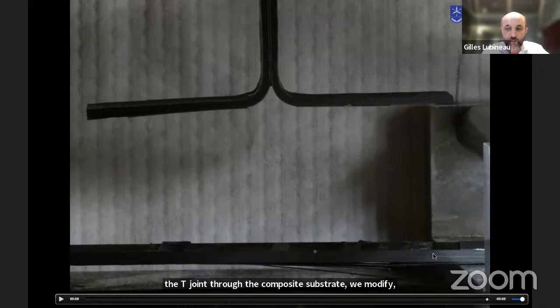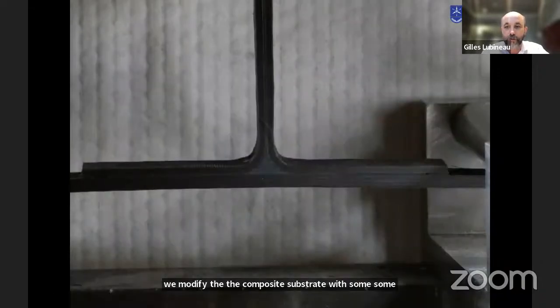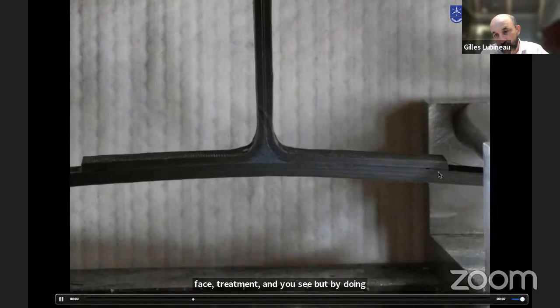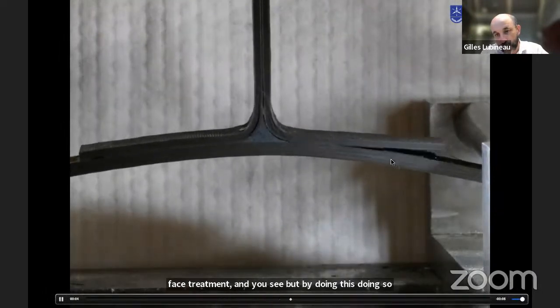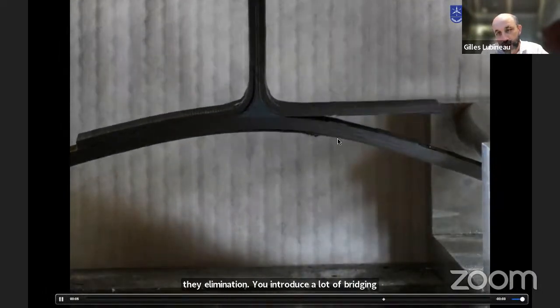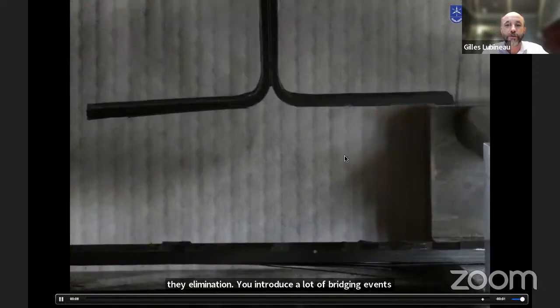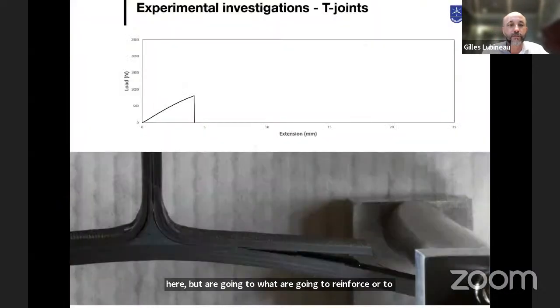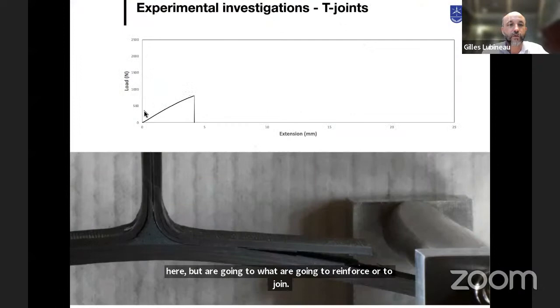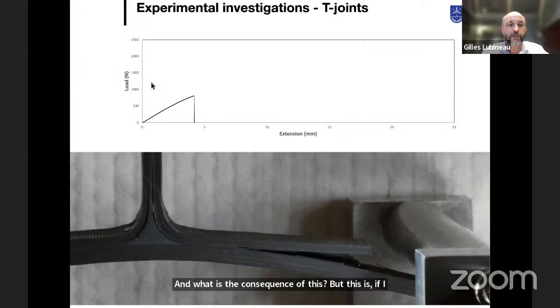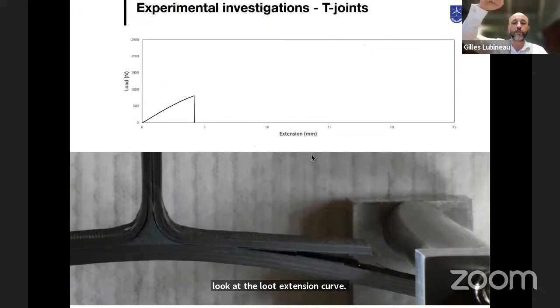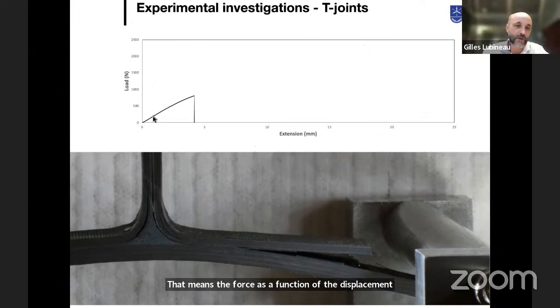the composite substrate with some surface treatment. And you see that by doing this, during the delamination you introduce a lot of bridging events here that are going to reinforce your T-joint. And what is the consequence of this? If I look at the load extension curve, that means the force as a function of the displacement when I pull on this T-joint, this is the original curve, the black one.